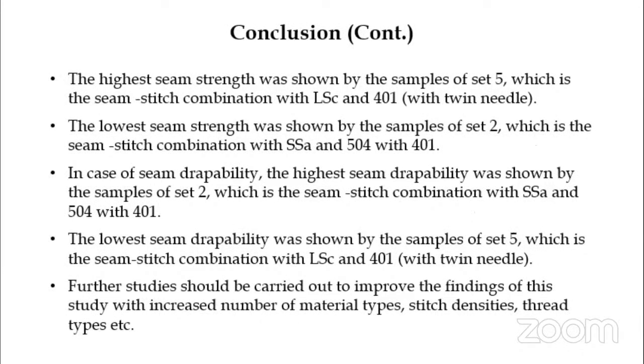The highest seam strength was shown by the samples of set 5, which is the seam stitch combination with LSC and 401 with twin needle. The lowest seam strength was shown by the samples of set 2, which is the seam stitch combination with SSA and 504 with 401. In case of seam drapeability, the highest seam drapeability was shown by the samples of set 2, which is the seam stitch combination with SSA and 504 with 401. The lowest seam drapeability was shown by the samples of set 5, which is the seam stitch combination with LSC and 401 with twin needle.